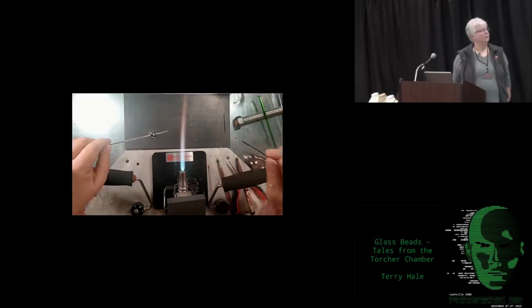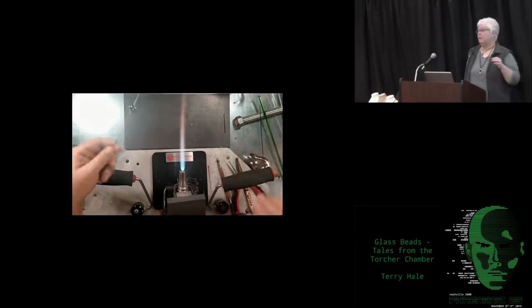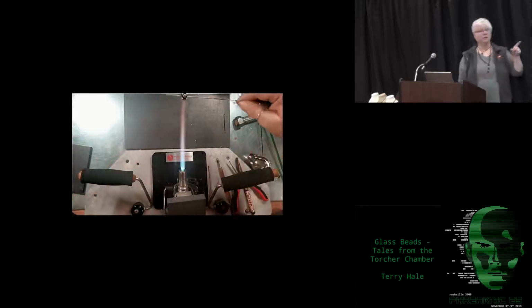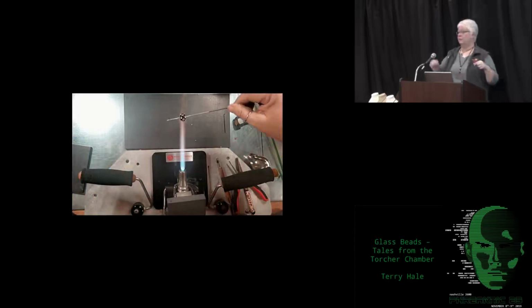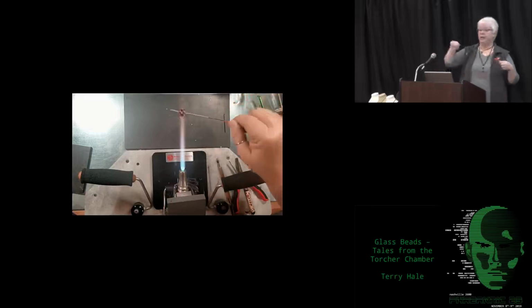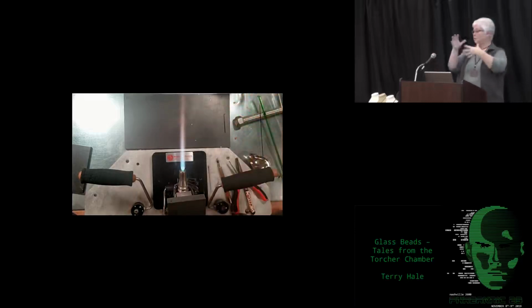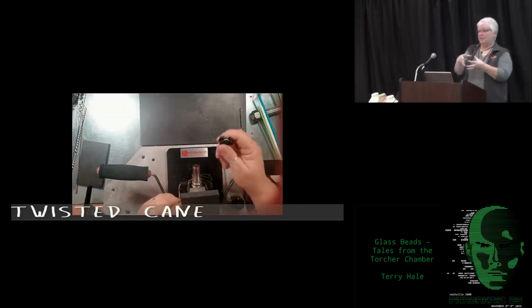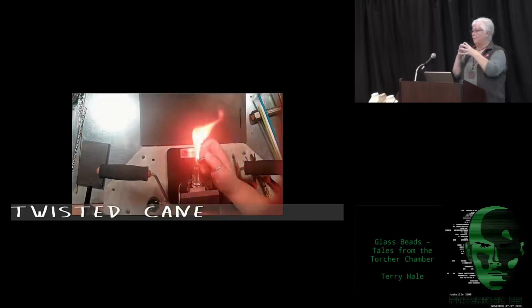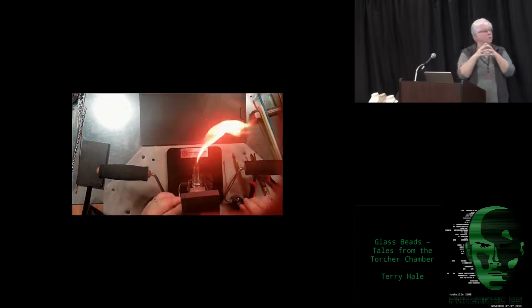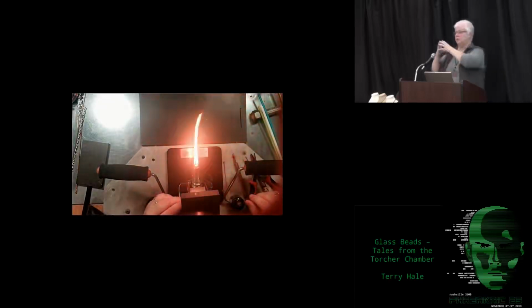And then when I finish a bead, it goes into a kiln. If I were to put that down on the table or in a bucket of sand or vermiculite to let it cool, there's a lot of stress in the bead. When you put the bead in the flame, you get it really, really hot, so those molecules are really going crazy. And then you pull it out to decorate it, and they freeze and shake. And then you put your decoration on, you go back into the flame, and they start moving again. And once they're so excited, you can never get them lined up again, so there's a good network holding that bead together. So what I do is take it, when I'm finished, put it in a kiln.